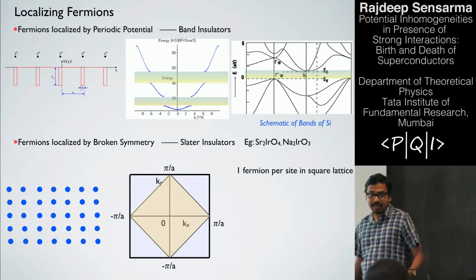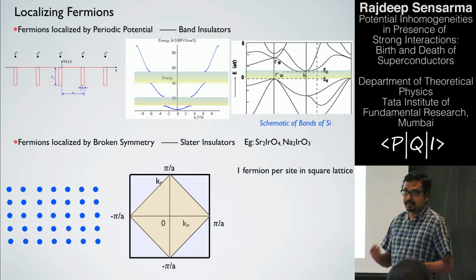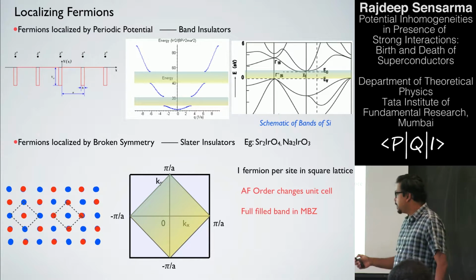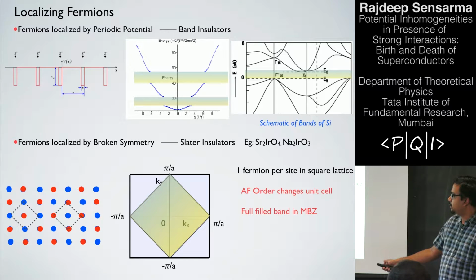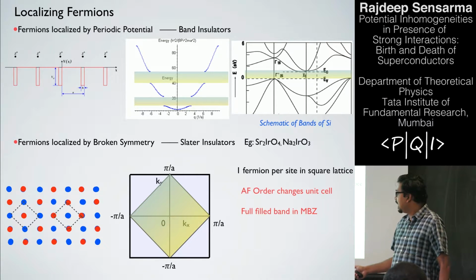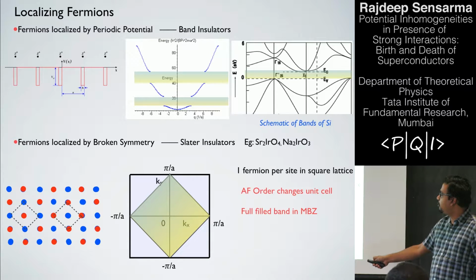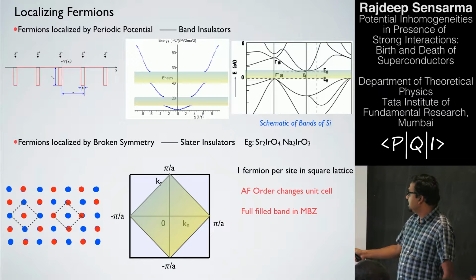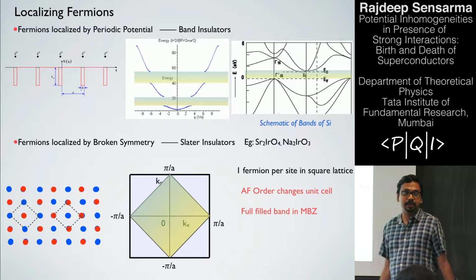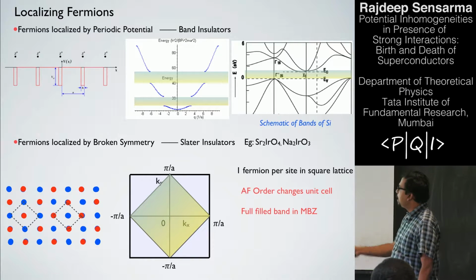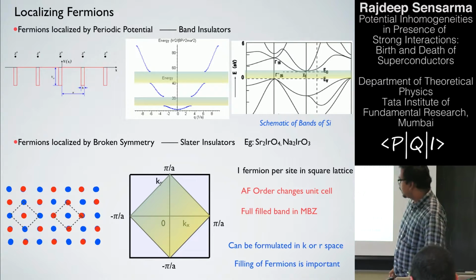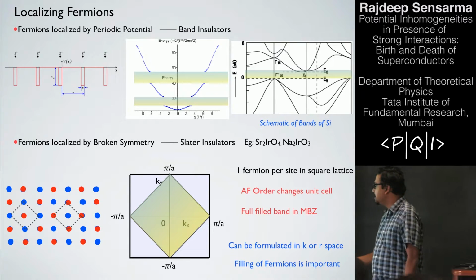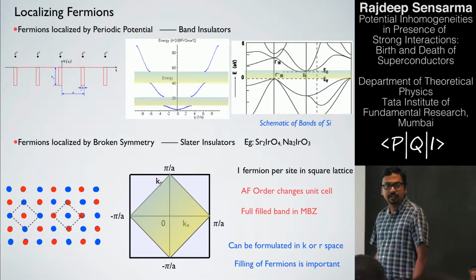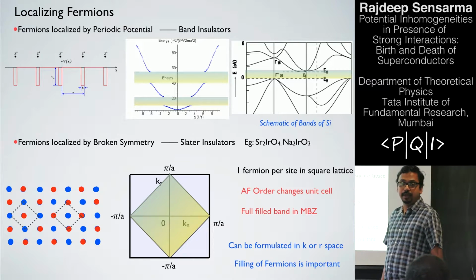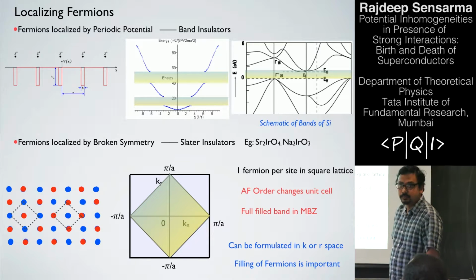However, if by chance, due to interactions, you introduce antiferromagnetism in the material, which means that spins prefer one sublattice over the other, so let's say up, down, kind of an ordering, then the unit cell is changed. In the new unit cell, this object is the full Brillouin zone, which is called the magnetic Brillouin zone. Within this magnetic Brillouin zone, the band is completely filled, and you can basically apply the theory of band insulators to this modified band. You can formulate this in momentum space or real space. You remember that the filling of fermions is important here, but these are two very simple ways you can make insulating states. So why do you call it a Slater insulator?